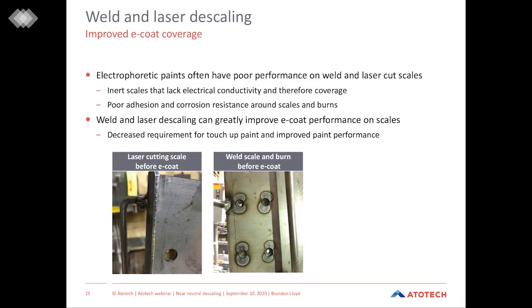So it also offers improved e-coat coverage. For electrophoretic paints, they often have poor performance on weld and laser cut scales. These inert scales lack electrical conductivity and therefore the coverage as well. Poor adhesion and corrosion resistance around the scales and burns is also an issue. So weld and laser descaling can greatly improve the e-coat performance on these scales. What this results in is a decreased requirement for touch-up paint and improved paint performance as well.